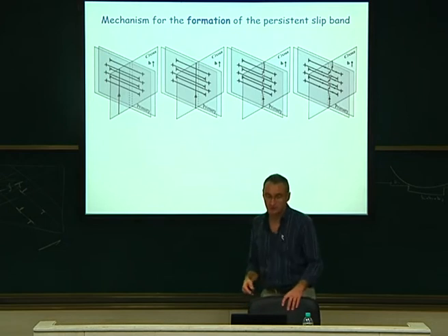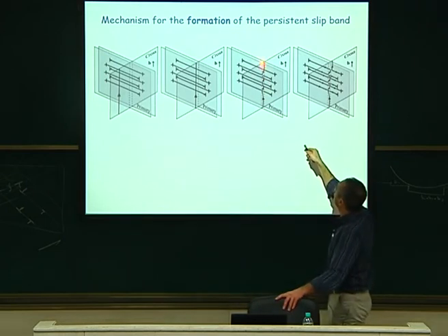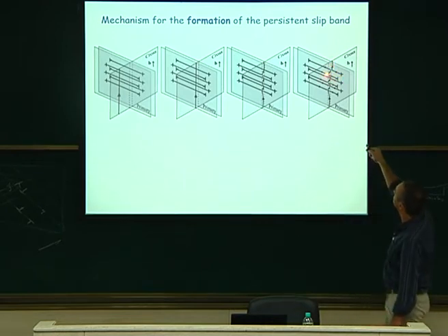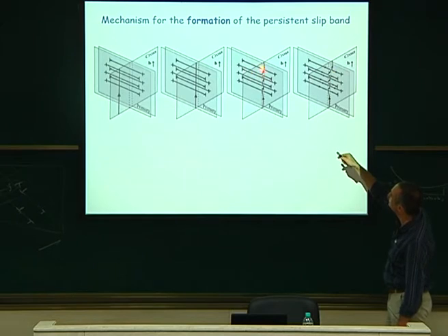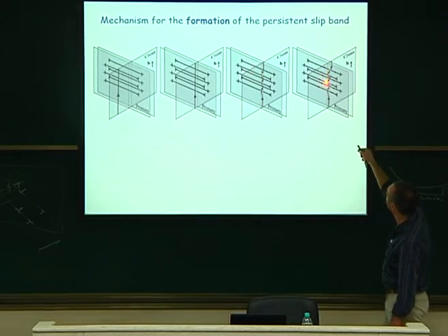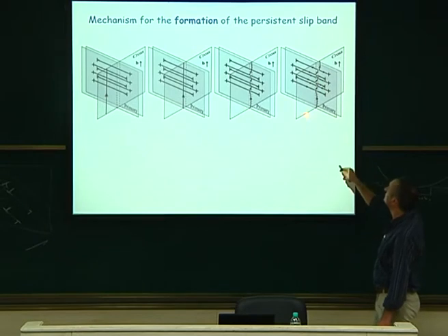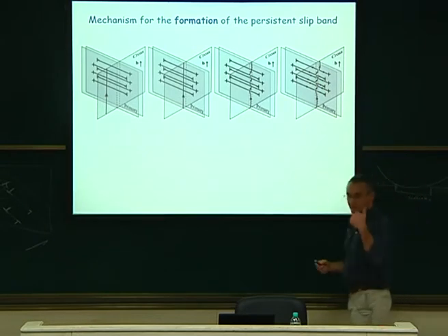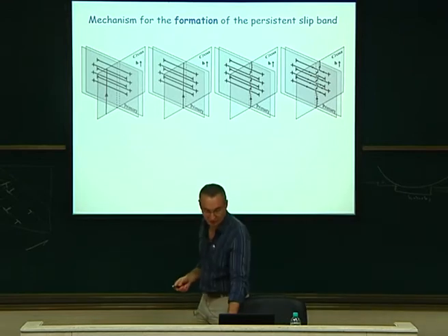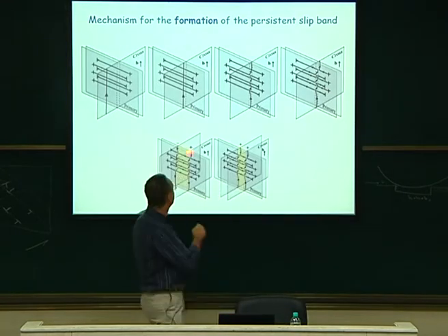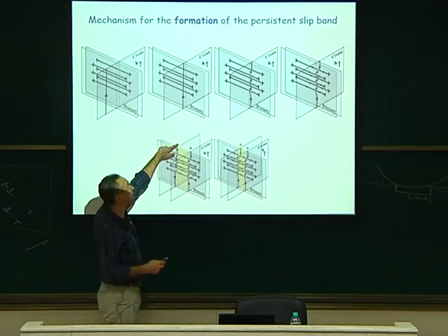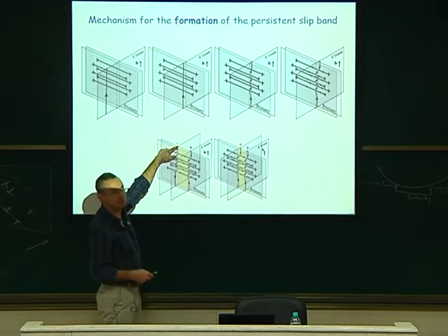Now if you go further, the dislocation will cross the second plane here and recombine again in that plane, okay. So now you have some small connection between the line on the first plane and the line on the next plane, like that, the same here. So this is the effect of shearing of your dislocation inside this vein. This is the case for a single dislocation. When you have a second one which is coming in a nearby plane, or even a far away plane, if it's the opposite sign dislocation, you can make the same topography.